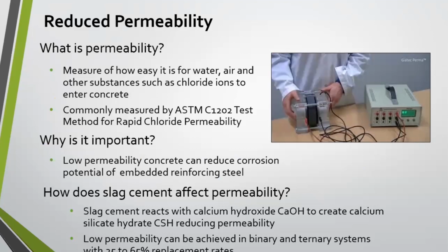What you're looking at in the picture on the right is basically a 2-inch wide slice of a 4x8 cylinder. We won't get too much into how it's prepared, but basically you've got a sodium chloride solution on one side, sodium hydroxide solution on the other, and you're running a current through this. Then we measure charge in coulombs. The lower the coulomb values from this test, the lower the permeability of our concrete.